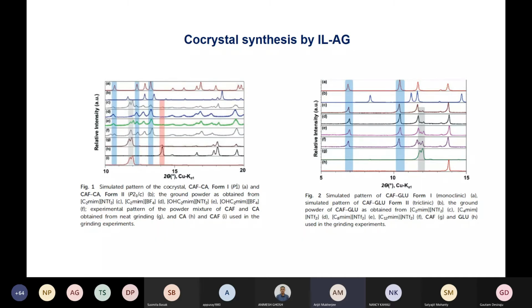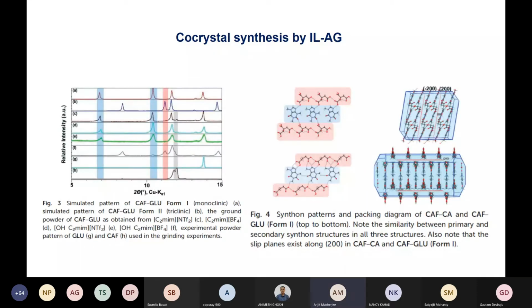So by changing the hydrophilicity or hydrophobicity of the ionic liquid, you can actually tune the polymorphic outcome. So that was a nice result, and it tells both things: that the nature of ionic liquids matters in this ionic liquid assisted grinding technique, and that it is a valid liquid for liquid assisted grinding. So we thought to analyze further why this form 1 of the glutaric acid co-crystal and the only form of the caffeine citric acid co-crystal showed similar tendency towards the ionic liquid solvents.